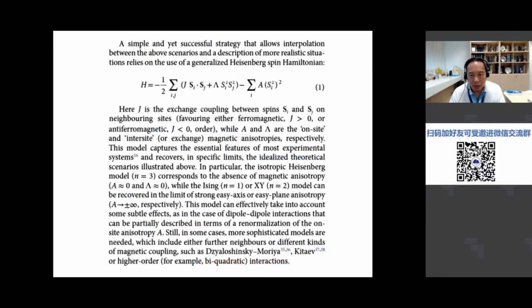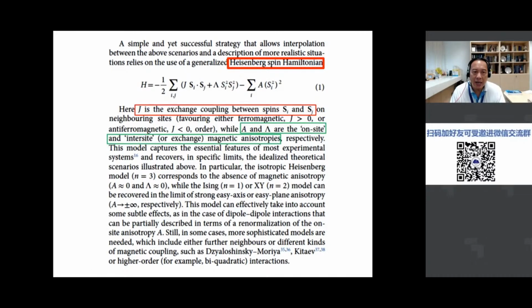So the only equation I'll show here, basically what I've mentioned about spin dimensionality, can be summarized by this generalized Heisenberg spin Hamiltonian. So you see in this equation, three terms. The first term is J, where J is the exchange coupling between spins Si and Sj on neighboring sites, okay? And if J is greater than 0, it's ferromagnetic. If J is less than 0, it's anti-ferromagnetic. So this is the basic basis of magnetism. But you have two other terms, A and Lambda, which are known as the on-site and inter-site or exchange magnetic anisotropies respectively. So A is the on-site and this is the exchange, right?